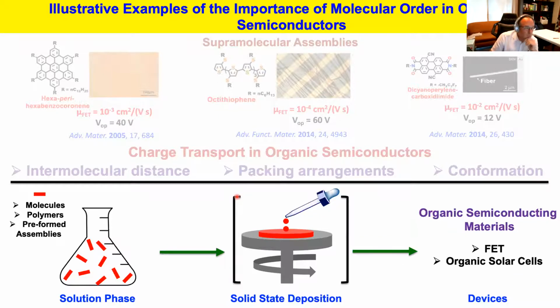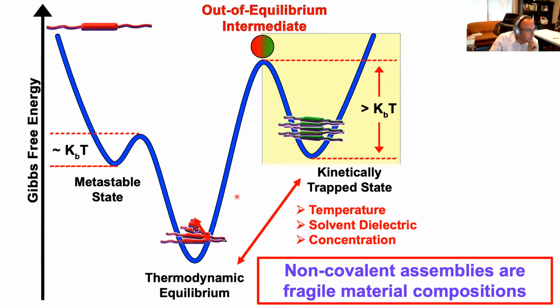And so that leads me to one of the big statements that I'm usually making, right, which is: non-covalent assemblies are fragile material compositions, okay? And what I mean by that is, if I'm starting on this very oversimplified energy landscape profile, I can start up there with molecularly dissolved building blocks, and I can either decrease temperature, change the solvent dielectric, or change the concentration of these building blocks. And eventually I'm gonna start sampling this energy landscape. And I may reach, for example, a thermodynamic equilibrium,